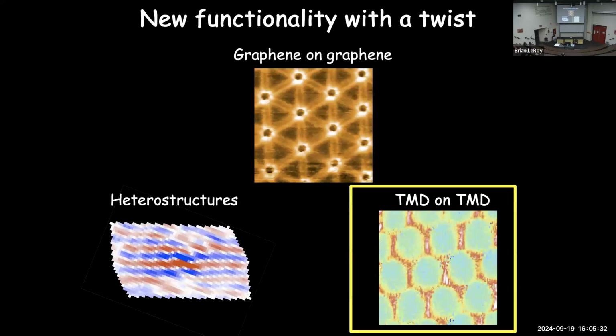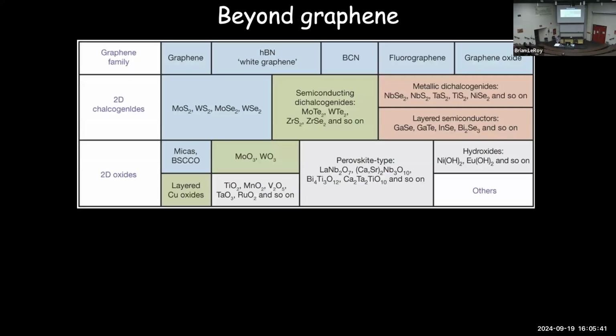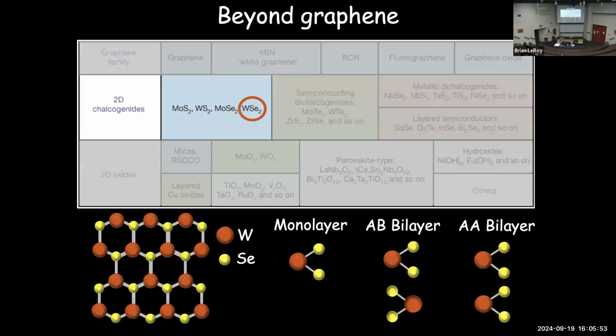All right, so now let me move on and talk about what happens when you take two TMD materials and you do the same kind of twisting on them. As I said, there's this range of materials beyond graphene. I'm going to focus just on these 2D chalcogenides for this talk. Their structure is a little bit different than graphene. If we look at it from a top view, it still looks the same, right? It's still got this honeycomb or hexagonal type structure. And in the monolayer, we have our metal atom here, tungsten, and the two selenium atoms like this.